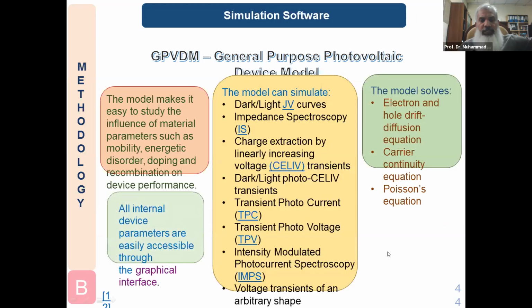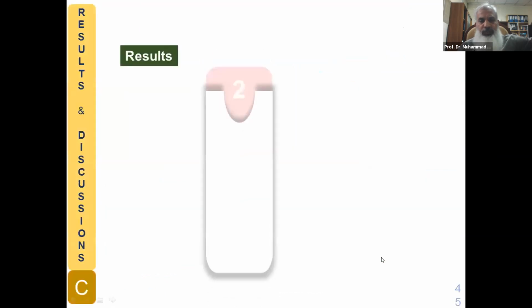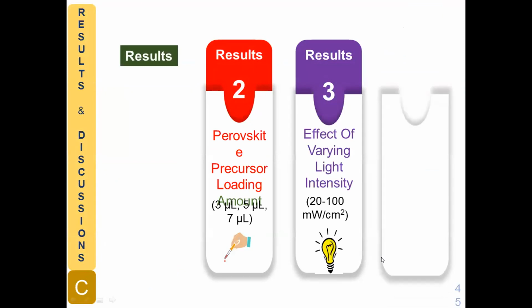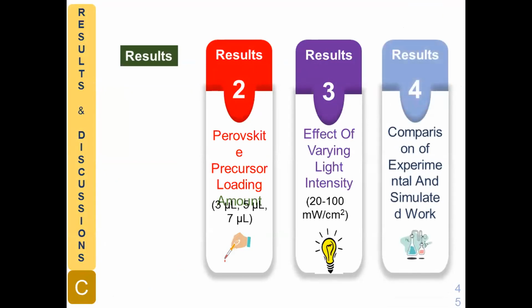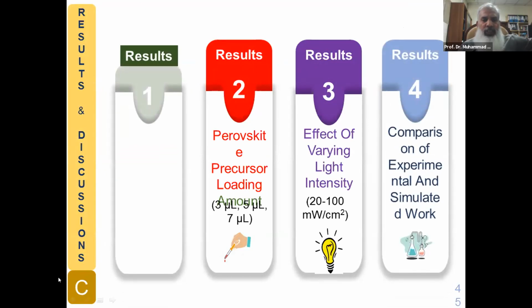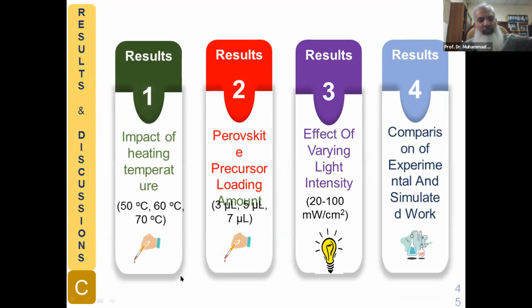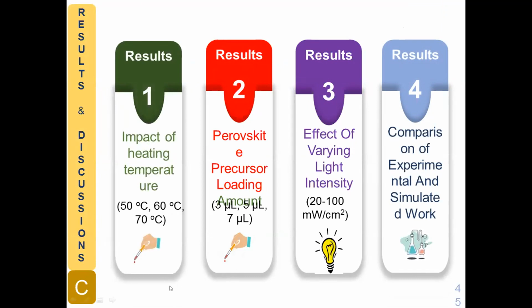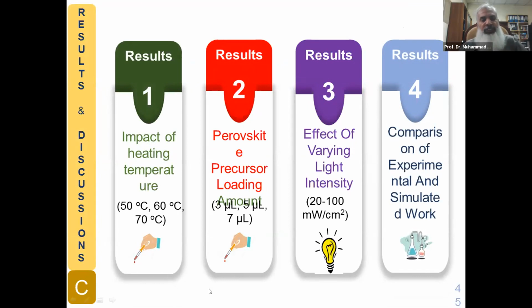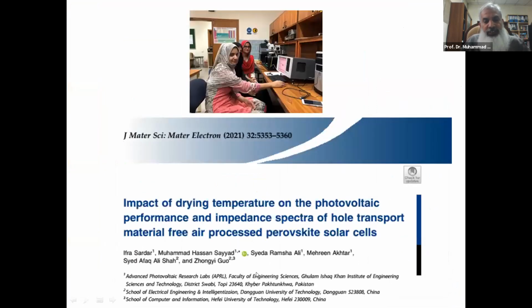So that was the software, freely available, which we have used for simulation. I will be just sharing results of this first one, impact of heating temperature. So we have heated the perovskite film at temperatures of 50, 60, and 70 degrees Celsius. And the optimum performance was obtained corresponding to heating of 60 degrees Celsius.